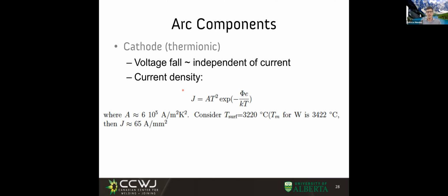Okay, so thermionic emission is a way of losing electrons that all materials have. All materials can lose electrons by thermionic emission. But here's the catch. To emit by thermionic emission, you need to be really, really hot. So although all materials can lose electrons by thermionic emission, not all materials can exist at the high temperature that is needed. They can melt and they can vaporize. So there are few materials that can have thermionic emission without vaporization. One of those is tungsten. So typically people say that thermionic materials are refractory. And what it essentially means is refractory materials can have thermionic emission without evaporating.